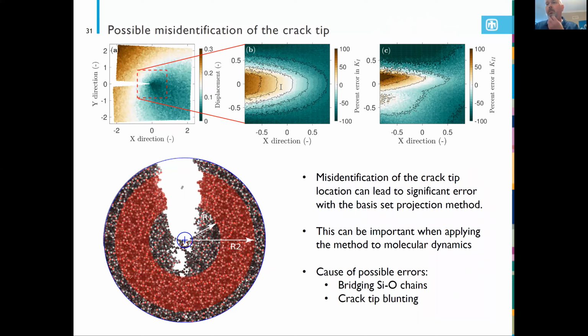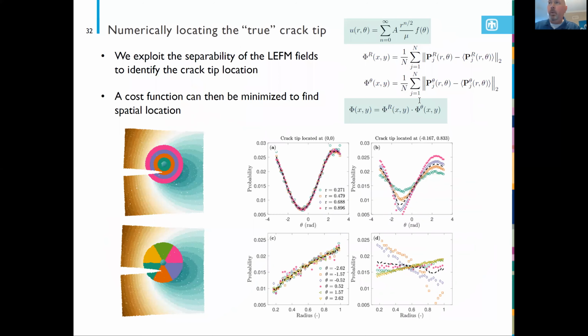And so what we've done is we've used a methodology. I had mentioned the separability of the Williams expansion, and what I've done is look at radial displacements. Given that they're separable, at any radius an angular displacement should be equivalent, and vice versa: at any angle, any radial displacement should be equivalent. Using that idea, we can map out the space and find the ideal crack location where the Williams expansion is the most separable. We identify that location as the true, quote unquote, crack tip location. From there, we apply the methodology.